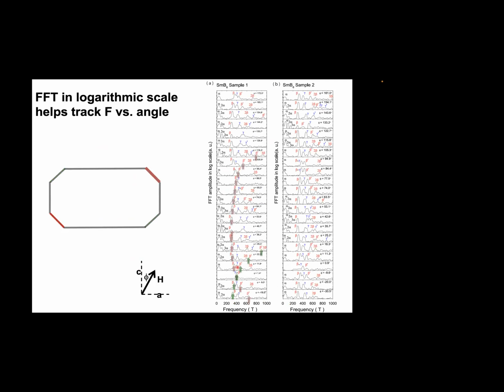One particular thing we look at in this evolution is that the minimum happens at about 45 degrees here. That would be exactly when the field is along this 011 axis. It's either coming from these surfaces or from elongated ellipsoids or cylinders along this axis. All right, the other sets. Out of this family, we further have the dispersion of this family. So one set, another set, again the minimum happens at about 90 degrees, which means we know these orientations are marked by these two surfaces. And this set.